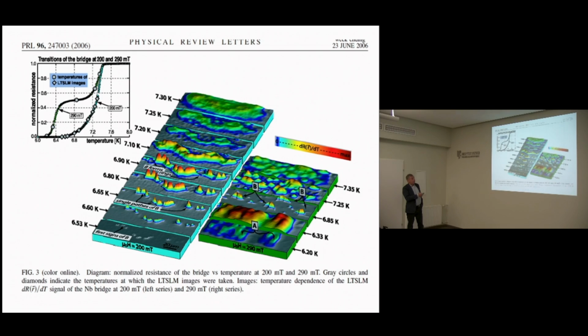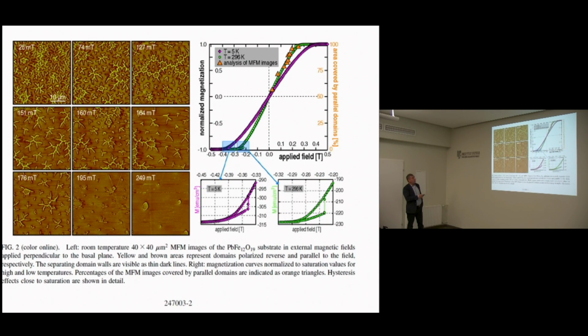If the magnetic field is increasing, this branched structure disappears, or the area of reversed domain becomes smaller, and then close to saturation, which is around 260, if I remember, then we have only the bubble. And a similar situation as previously, the magnetization curve was made at 5 Kelvin and at room temperature. So they are very similar. That's why the authors assume that the domain structure at 5 Kelvin is similar to that at room temperature.